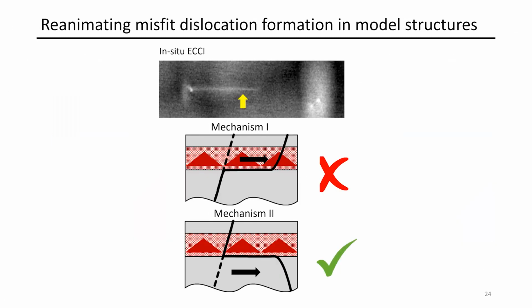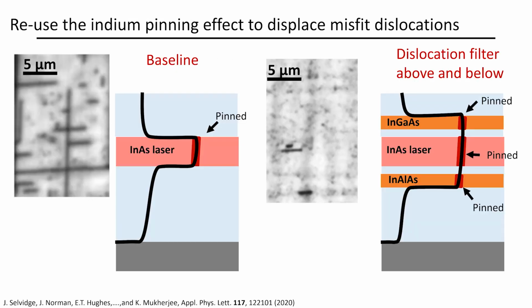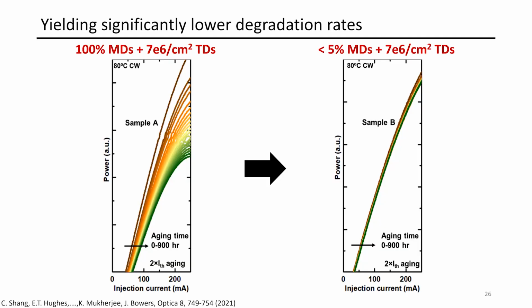Here's the mechanism. We actually confirmed that this is actually what's happening. The misfit dislocations do form during cool down, not during growth. And once you see that this is happening, you use a simple strategy. You said, wait, if indium pins it, let me reuse that pinning effect. So I'm going to put an indium-containing dummy layer above it. I'm going to put an indium-containing dummy layer below it. And I'm simply going to displace where those horizontal segments form. That's all. And the moment we did that, the laser death got reduced significantly.